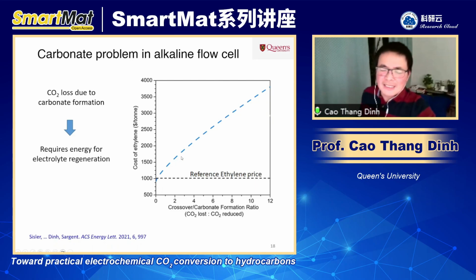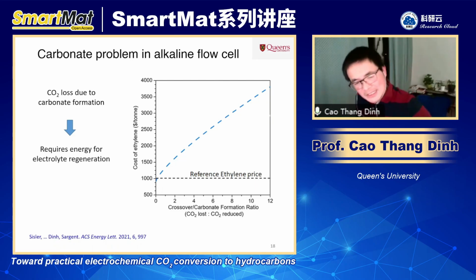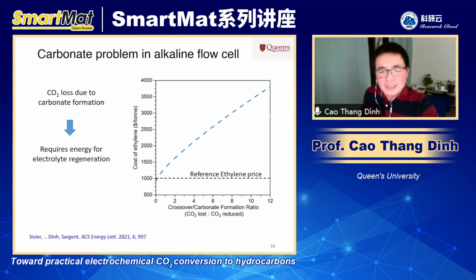So we did some calculations to see, if you have CO2 crossover, if you have CO2 converted to carbonate, how much energy you need, or what would be an acceptable ratio. The result is that if the cost of ethylene is $1,000 per ton, then you should have a very small amount of CO2 converted to carbonate or crossover. Otherwise, the energy consumption is way too much. So based on this, in order to reduce the carbonate formation, the best way is to run the reaction in a neutral or even acidic condition, so that you can prevent carbonate crossover or formation.